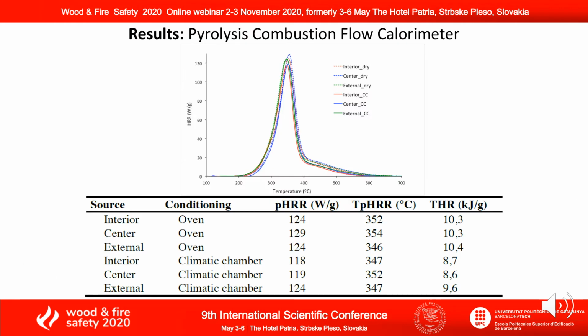In the pyrolysis combustion flow calorimeter, we observe that the heat release rate is influenced, as expected, by the moisture content, leading to a lower value of total heat release rate, but no significant difference is observed according to the section at which the sample was extracted.